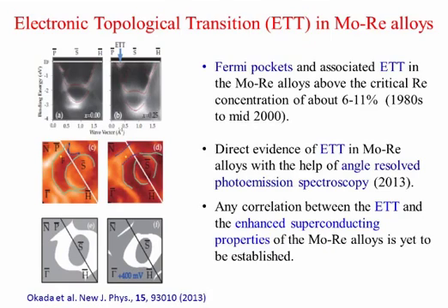In a parallel development, the existence of Fermi pockets and the associated electronic topological transition (ETT) have been established in the molybdenum-rhenium alloys above the critical rhenium concentration of about 6 to 11%. However, any correlation between the ETT and the enhanced superconducting properties of these alloys is yet to be established.